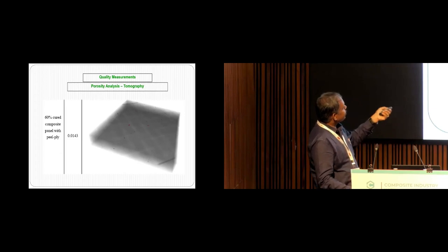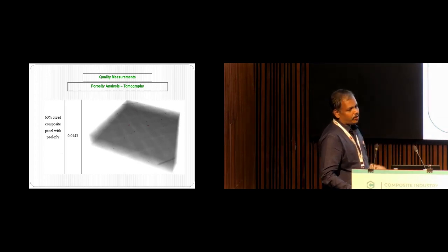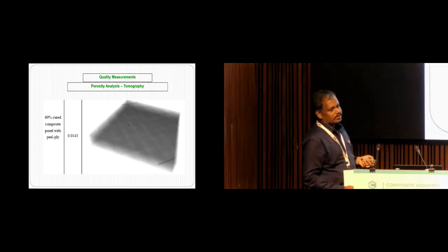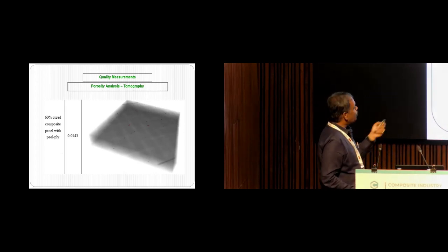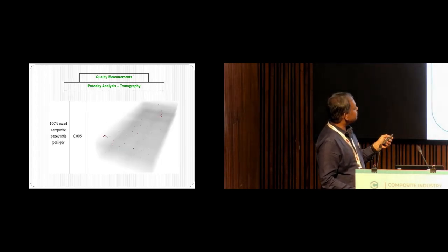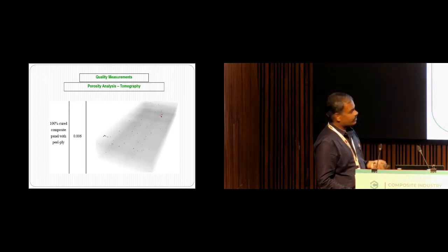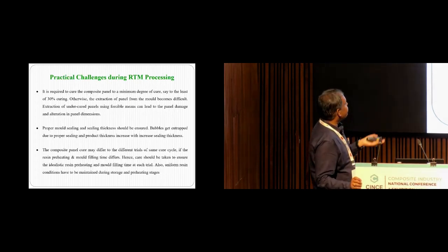So for 60% cured composite, we try to find out what will be the change in the pore volume percentage at different cure levels. For 100% cure, again it is 0.006%. So there are certain observations.